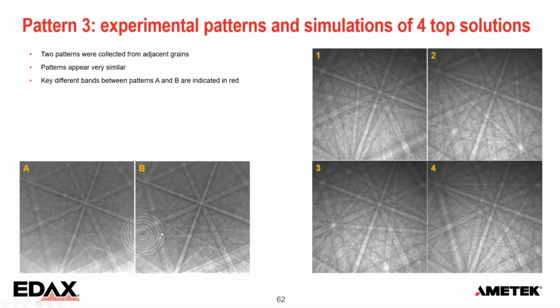between those orientations that if you go to normal low pattern resolution indexing, the software will never pick up. So when I index those, here I indicated the bands of interest to look for. And when you look at those in the simulations, we are seeing them here as well. And in the simulations, they are actually much cleaner. And that tells you something about the formation and the phase behavior of the material. My suspicion here is that some of those bands are related to stacking faults. So if you have some stacking faults, they go fuzzy and they disappear. And in the simulation, we don't have that. We are assuming a perfect crystal.